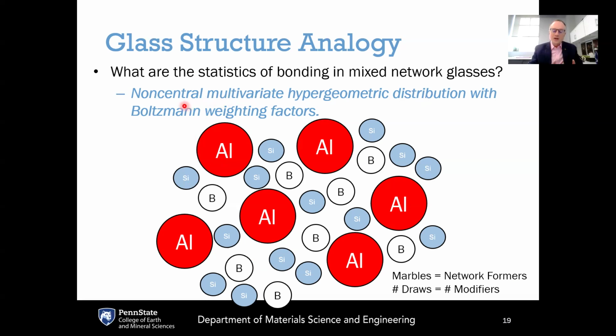It's non-central because the individual atoms have different weighting factors because of their different energetics. That's why it's non-central. It's multivariate because there's more than two choices here. We've got three different types of marbles that are the three different types of network formers in the glass. That's what makes it multivariate. It's hypergeometric because this is done without replacement, meaning that once a sodium ion associates with an aluminum, that aluminum is no longer available to associate with another sodium because that bond has already formed. That's why it is a hypergeometric distribution.